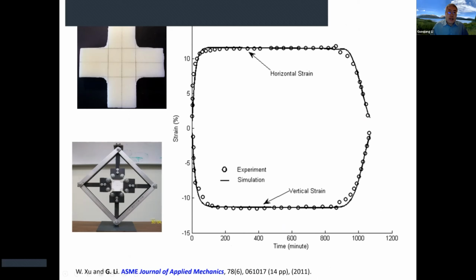And we also did two-dimensional loading. For example, in this device, you can see in the vertical direction is compression, in the horizontal direction is tension. Our model, again, can reproduce the two-direction programming and shape recovery process. Recently we also use a two-way shape memory polymer as a matrix, and we extend the applications to not just the core for sandwich structures, but also sealants for cracks and joints. And we are looking for more applications and more potential to collaborate with industry partners.